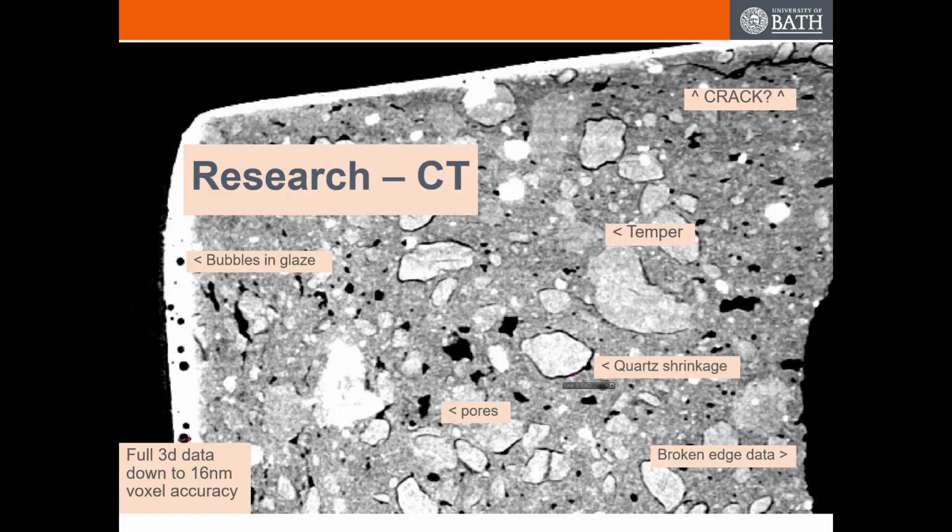I've got some bricks in my sample data set just to maintain an edge, so I can see where I'm coming into something that's very like a red stock brick. And I do have samples that are unambiguously terracotta. They're a window jamb that was rolled as a sausage and infilled with concrete. It's got exactly the same porosity as a brick and almost exactly the same porosity as a cheap terracotta flower pot.